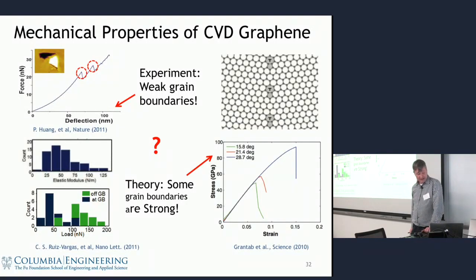And we came into this, this was again in maybe 2010, 2011, there was a little bit of a disparity in the literature. There was some initial experimental work showing that CVD graphene was very, very weak. So these loads, instead of being thousands of nanonewtons for breaking, were tens to hundreds of nanonewtons, and you saw lots of hysteresis in the force displacement curve. So something certainly looked like CVD graphene wasn't very strong.